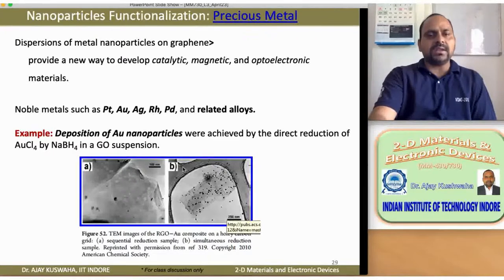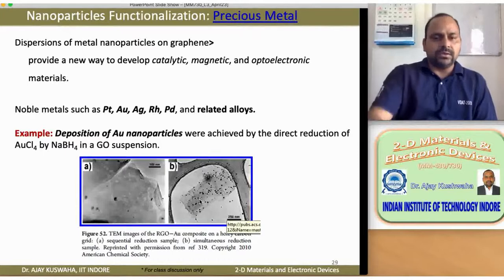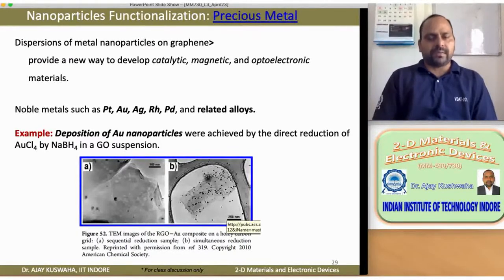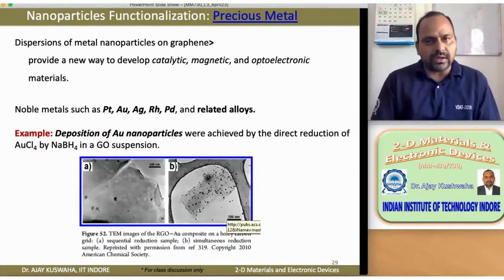So in B, this is a TEM image just to show that these black dot spots are the gold particles, and this is the sheet of graphene. Similarly here, this is the sheet of graphene. Here you can see the density of gold particles is higher, and also the diameter, the shape of the gold particles is though not very uniform, but at least the size does not look so much varying. So this is the second, when during the exfoliation of graphene oxide, they are doing the gold nanoparticle reduction. So they are calling it in situ. So this is one way to demonstrate how gold nanoparticles can be decorated over graphene oxide.